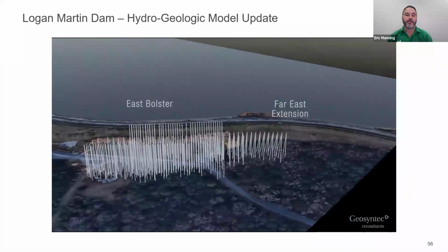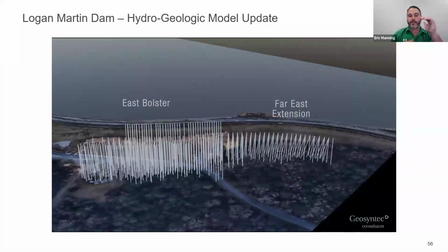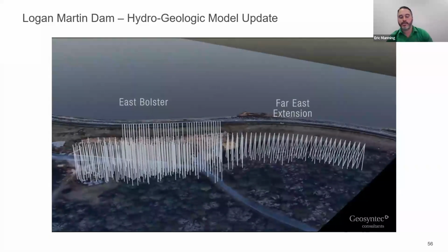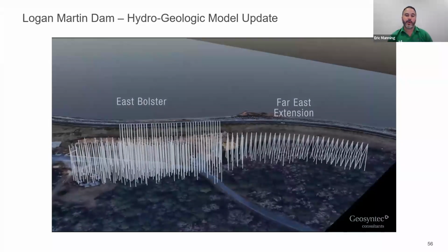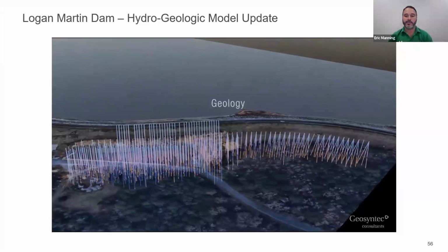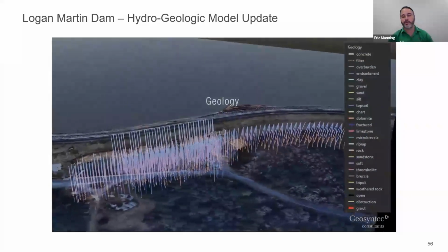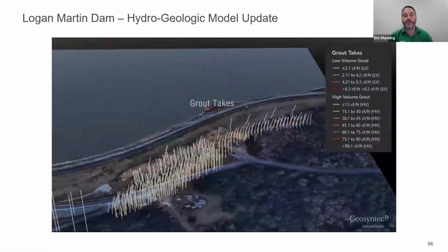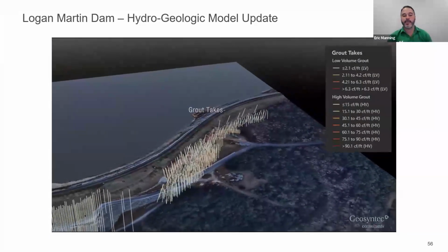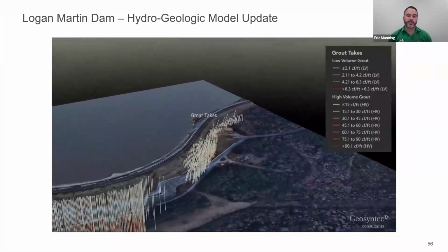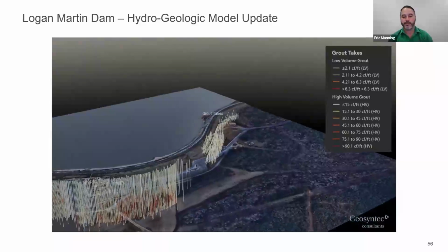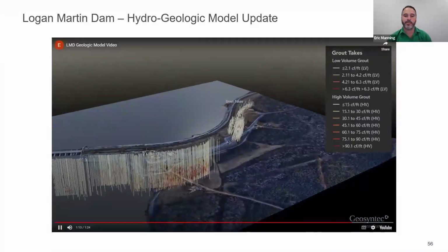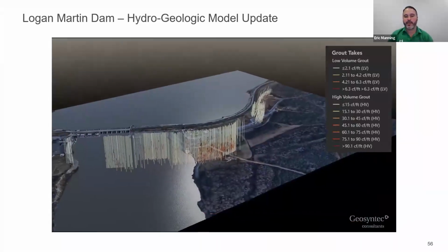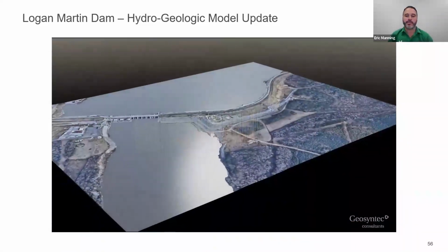And what we found as we were drilling the east bolster was that the minimum rock cap that we needed for stability, based on our calculations, we didn't meet that. The rock cap that we needed for sufficient support was 2 foot. And what we noticed in most cases was it was much less than 2 feet of a solid rock cap. In a lot of cases, that top of rock was highly fractured. So we had to reduce our spacing down with interspaced holes on roughly 12 to 14 foot centers. We notice the same thing as you go farther east as well, and that's part of the next phase of grouting, where we're going to install those new interspaced holes where we had insufficient rock cap.